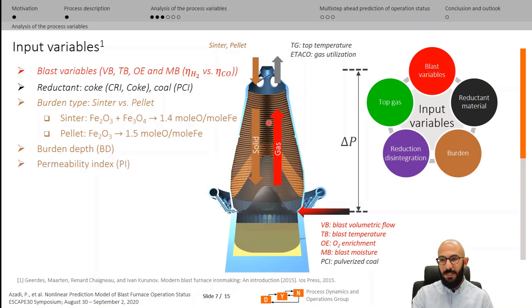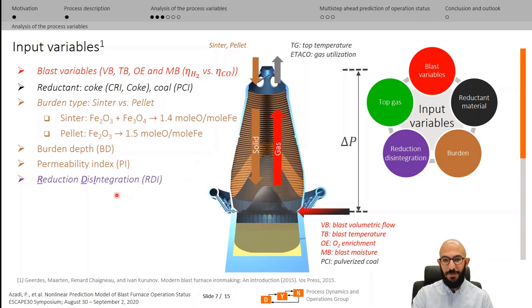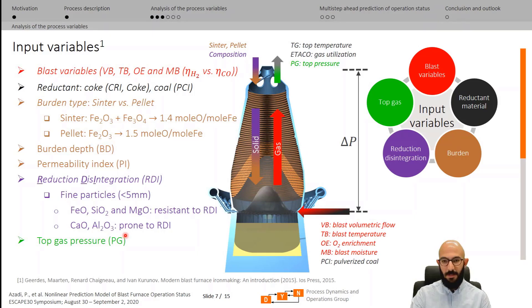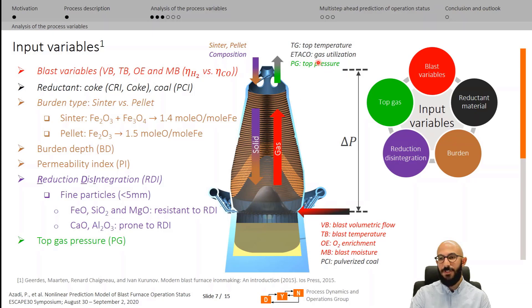The permeability of the solid bed, which influences the pressure drop and reaction conditions, is also affected by the reduction disintegration index (RDI) phenomenon related to fine particles of sinter. The composition of the sinter controls permeability and therefore the pressure drop and reaction conditions. In general, FeO, SiO2, and MgO make the sinter more resistant to RDI, while CaO and alumina make it more prone to RDI. The top gas pressure influences gas distribution and flow, the velocity of the gas, the contact time between gas and solid bed, and therefore the reaction conditions — detectable through the gas utilization factor.